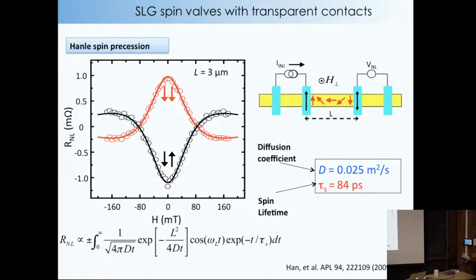And so what people typically do is they will fit these curves, and based on the fits, you can extract out the diffusion coefficient, and you can extract out the spin lifetime. So the typical way for people to get a spin diffusion length is to multiply these two numbers and take the square root. And they say, okay, that's the spin diffusion length. And so typically it's like 2 to 3 microns in these materials.